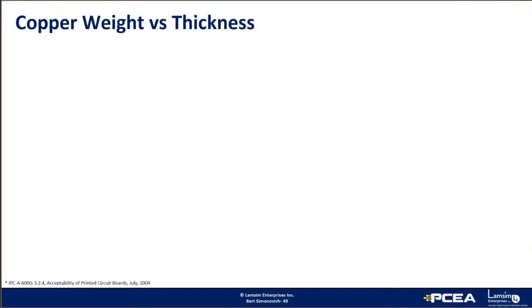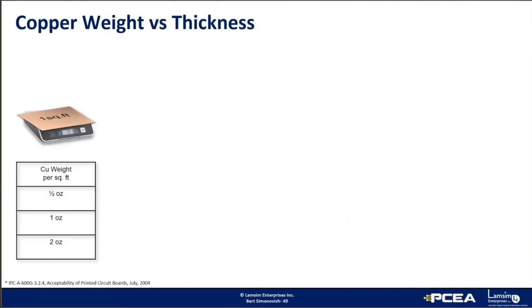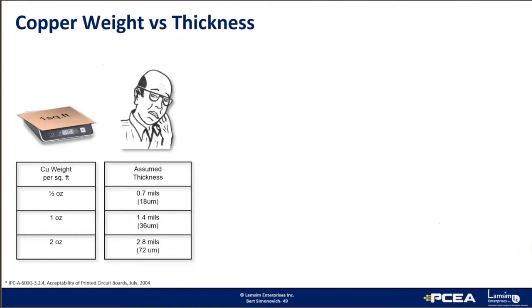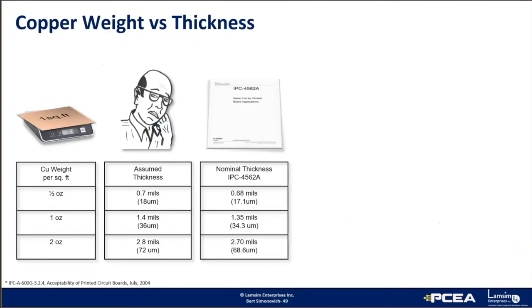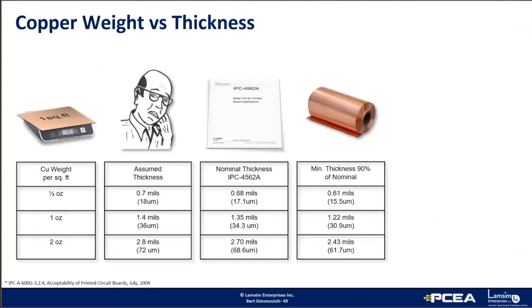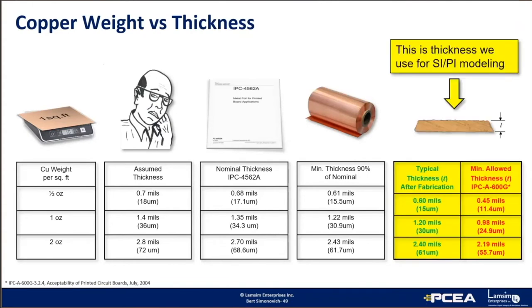Another important nuance with modeling is copper weight versus thickness. The thickness of the copper is based on the weight in ounces over 1 square foot of area. Most engineers assume the thickness shown here. But IPC-4562A actually gives a nominal thickness of plus or minus 10%, which means the copper you get will likely be on the low end of the spec because of the copper cost. Then by the time the PCB is processed, you will end up with these typical values. But after processing, the spec allows a further reduction. So these are the worst case numbers you should be using for your SI/PI modeling.